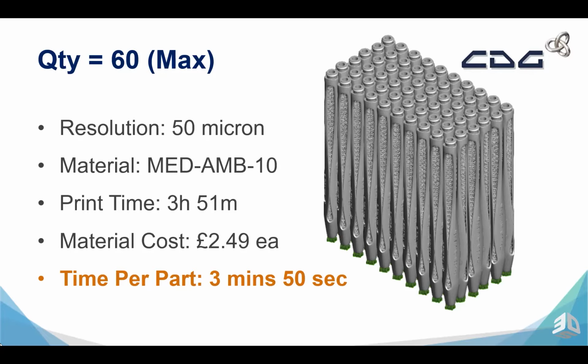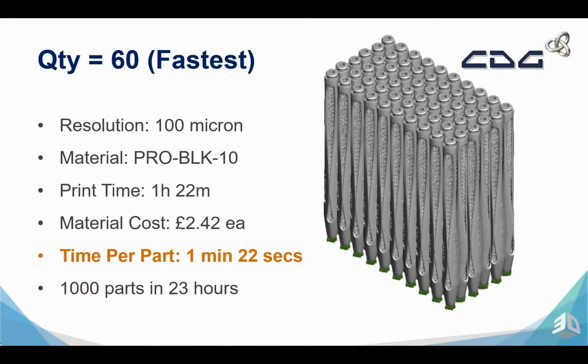Now, this is actually one of the slower materials that we have on offer. So let's see what we can do with materials such as Pro Black 10 at 100 microns. This is a very fast material with a higher resolution. We can reduce the print time down to 1 hour and 22 minutes for 60 parts, at £2.42 each, again, a reducing cost for this material. The time per part is 1 minute 22 seconds. Very, very quick. In fact, it means that we can produce 1,000 parts in 23 hours, less than 24 hours. This is amazing compared to a traditional aluminium tool where 1,000 parts would take 2 to 3 weeks to produce.